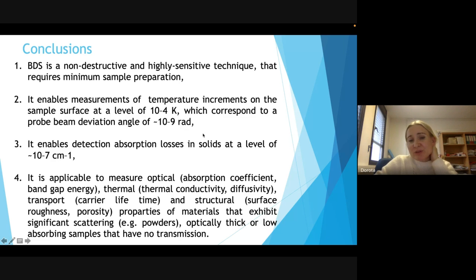It can also be used for a wide range of samples, including those that absorb very weakly, because it enables detection of absorption losses at the level of 10 to the minus 7. By its use, we can find optical parameters of the sample such as absorption coefficient or bandgap energy. We can determine thermal properties such as thermal conductivity and diffusivity, transport properties such as carrier lifetime, and structural properties such as porosity, as we saw in the presentation. It is applicable to a wide range of samples, also those that exhibit significant scattering, such as powders, are optically thick, or are weakly absorbing and have no transmission.